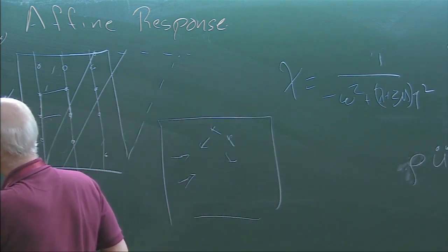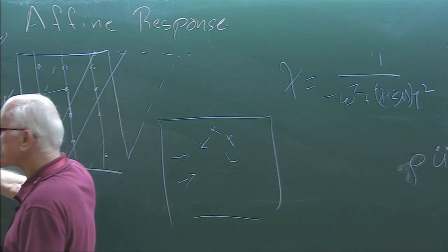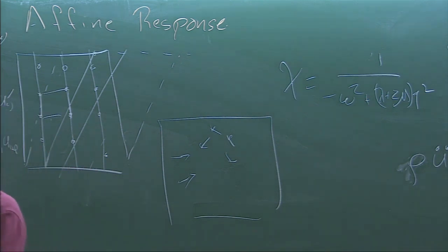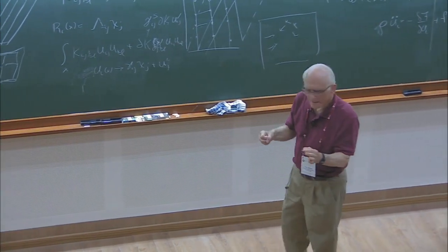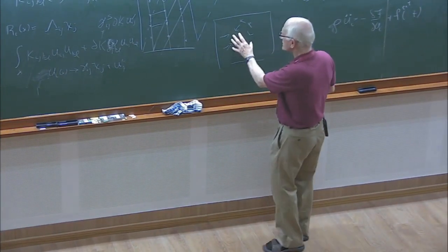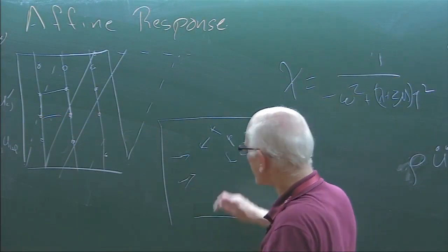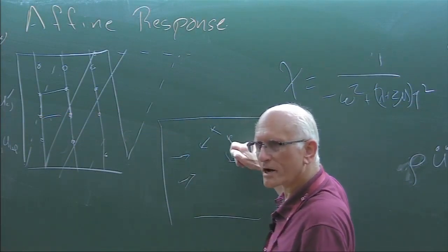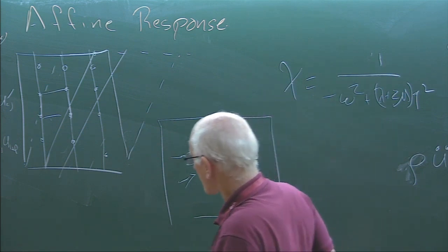Did we do this yet? No, I guess we haven't done it yet. So the delta K, the K depends upon the coordination number of a given site. So if I have a lattice that has six-fold coordination in some sites and four-fold and three-fold in other sites, then you have a random delta K, and you can do a calculation. And what happens there is you get very complex sort of vortex structures in the U prime displacement, which came about because of the strain.